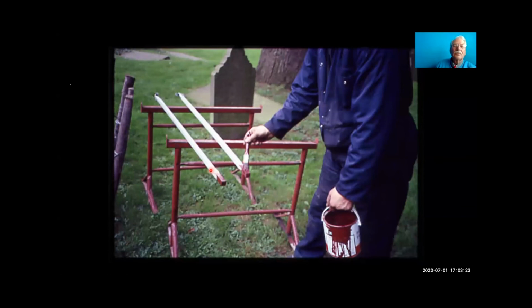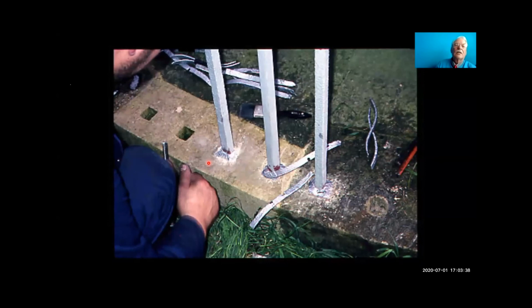So we chopped off the defective ends and fire welded on new pieces of recycled wrought iron. And here we're using an epoxy paint because when we come to lead these back in, the lead will try to burn off the paint, but epoxy paints will actually survive molten lead. It's very important to use this traditional fixing if that was there previously.